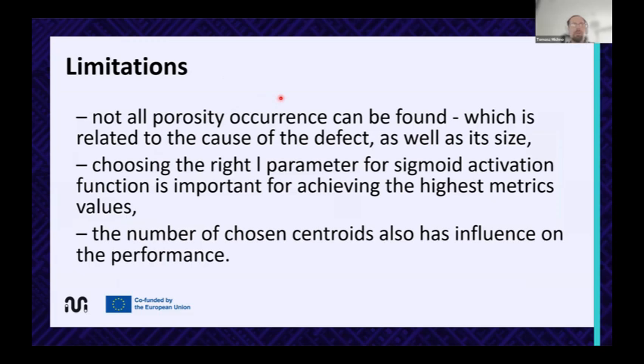And also this method from this paper has some limitations. So for example, because of different types of porosity, we can find only these ones which are connected to the thermal surface. So we are limited to only them. So for this shrinkage porosity type, gas porosity may be not so easily detected. And for this, we need additional data sources, like, for example, this average value or even time series. Also, choosing the right parameters and activation functions is very important. And the number of chosen centroids and types of them, so different types of clustering, has also influence on the performance.